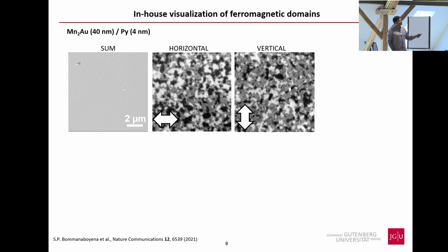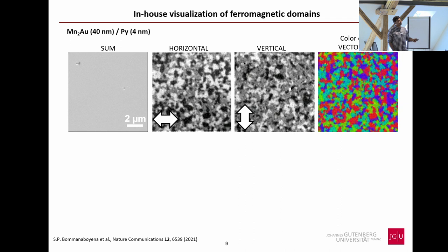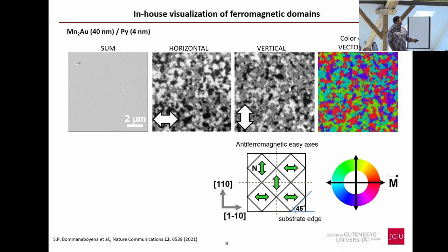The next sample used permalloy deposited on Mn₂Au instead of iron — 4 nm of permalloy on 40 nm of Mn₂Au. Starting again with the morphological image and then extracting horizontal and vertical magnetization components, the domains have the same shape and size (~1 µm average). When combined as a vector sum, completely different colors appear corresponding to different directions. Comparing the permalloy moments to the Mn₂Au underlayer, the magnetic moments are now non-collinear. This confirms that magnetocrystalline anisotropy was indeed responsible for the 45° biquadratic coupling.